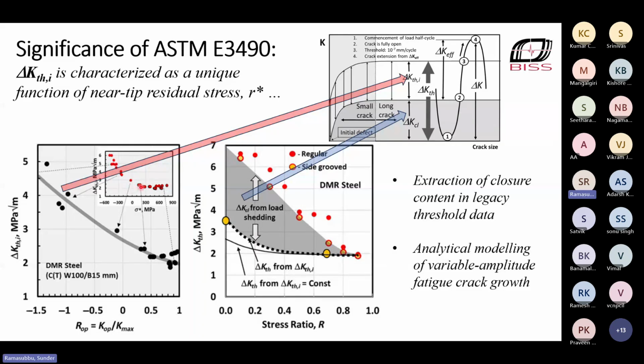Now, this relationship can be translated, analytically, purely based on equations, into ΔK threshold intrinsic versus crack opening stress ratio. Now, what is crack opening stress ratio? You can treat it as the stress ratio if there is no closure. So this will apply to initial defects. And if you want to look at long cracks, you look at the plot at the right, and you can see that the total ΔK threshold will be the sum of the closure component, which is given by the shaded area and is sensitive to how you perform the test, and the intrinsic component, which is over here.